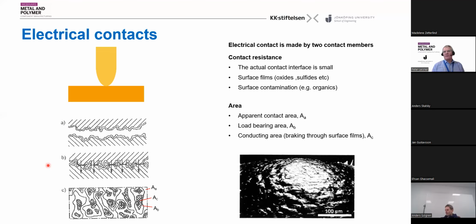But when you still have surface contaminants or oxide films, the current will not flow through the whole mechanical contact area. There will be even smaller spots, which we usually call A spots, which are the conducting area. As illustrated here, you have the whole apparent contact surface, you have islands where you have mechanical contact, and then you have even smaller islands where you have the real electric contact. And since it's narrowing down in the electric contact, you will have electric resistance. You can see on the other side a microscopic picture of a real contact. You can see there are micro roughnesses on the surface.